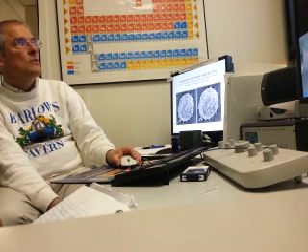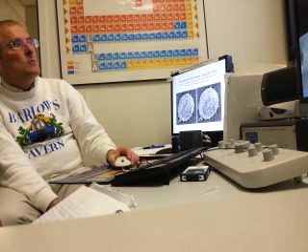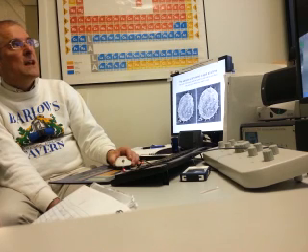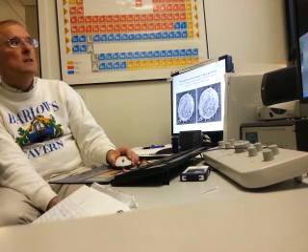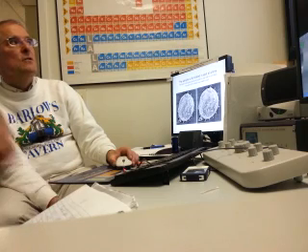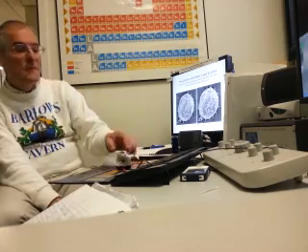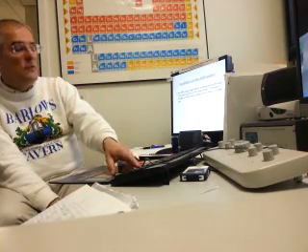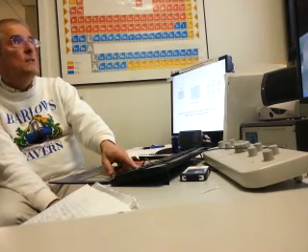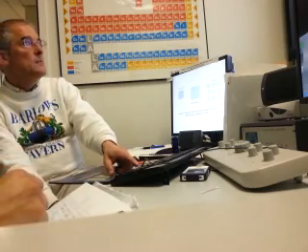This would just appear as a gray spot, so you wouldn't see these little things sticking up. If you make the dot smaller, then as you scan it across these smaller objects, you wouldn't be summing up the values to gray, and you would see a difference in intensity to tell you there was something there. So magnification has an effect if you keep your spot size the same.